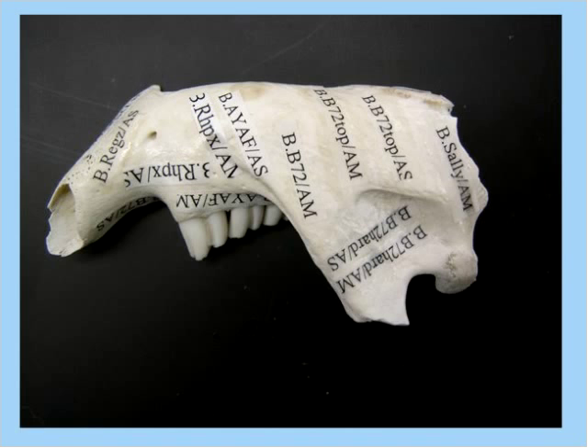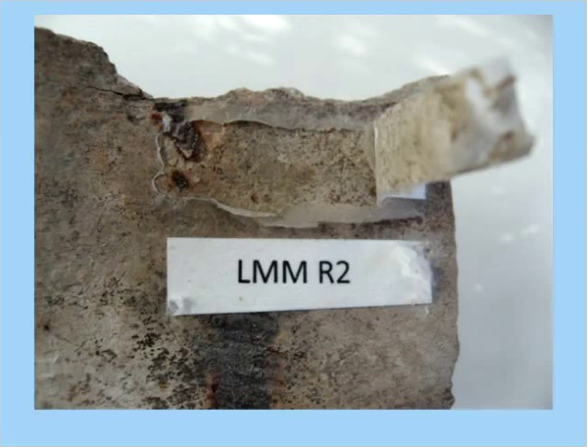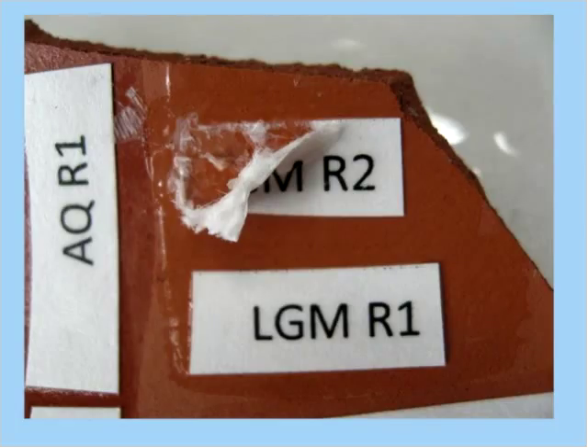Here's a piece of bone I had all these different adhesives applied to. This is what happens with a lot of water-based adhesives — they're water-based and easy to clean up in water when still wet, but when dry they're not reversible in water anymore. You have to use a solvent to try to reverse them, and they don't fully dissolve in solvents — they only swell up and become like a gel. With porous materials like bone, they swell up and get into the pores, and when you try to get the label back off, it peels off some of the surface of the bone because it's not fully dissolved, just turned into a gel. Here's one of those water-based labeling materials that just swelled up — you really have to scrape and peel and it's not coming off easily.